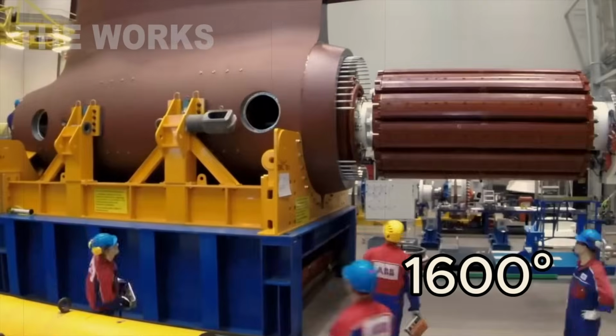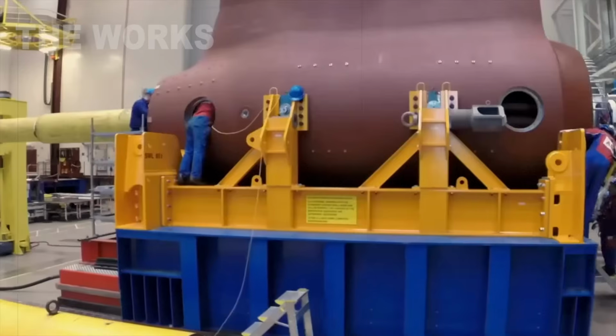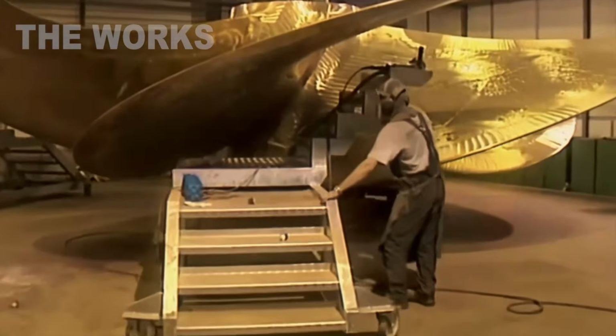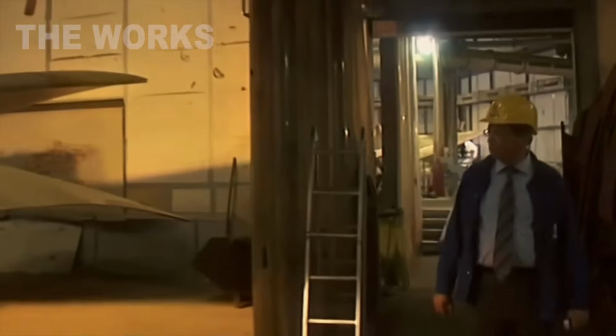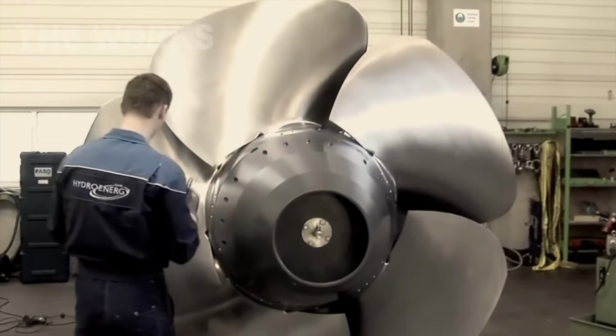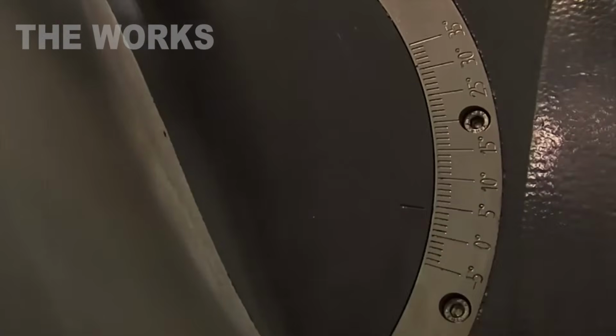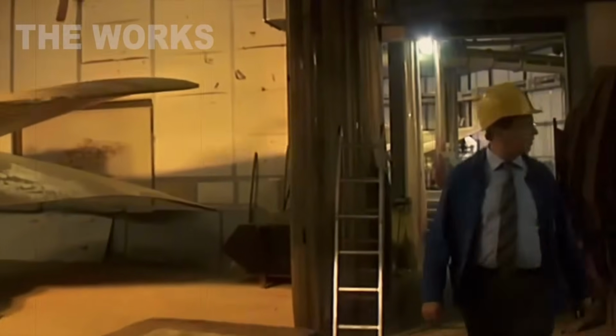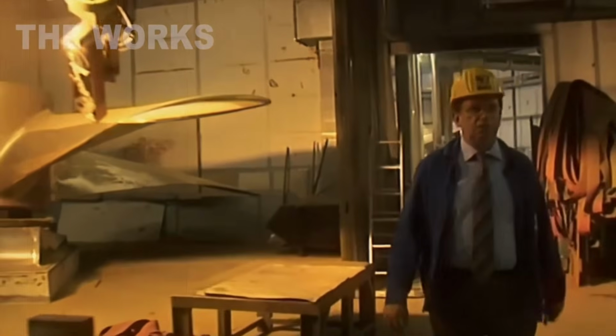The metal melts, glows orange, then white. The surface churns. The crew skims off slag, oxides and impurities floating to the top. They add alloying elements, manganese, nickel, aluminum, for strength and corrosion resistance. They pull a sample of the melt, analyze the composition. When everything's ready, they start the pour.